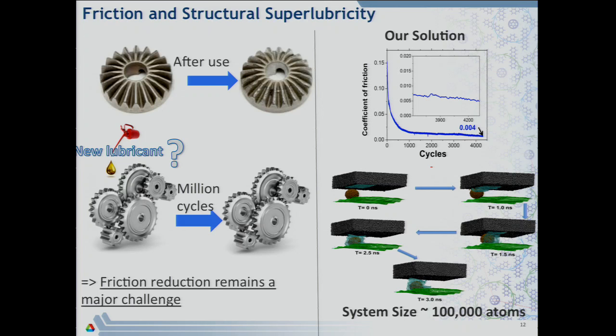When he looked at the friction, values dropped to almost 0.004. But the tubes were not stable — under the load exerted by the amorphous carbon, the tubes would fold onto themselves, causing the friction coefficient to jump up again. When averaged over time, the average friction would be higher, but the instantaneous friction would drop to very low values. We then figured out that if there was a way of stabilizing these scrolls, we could have a very stable superlubricity.